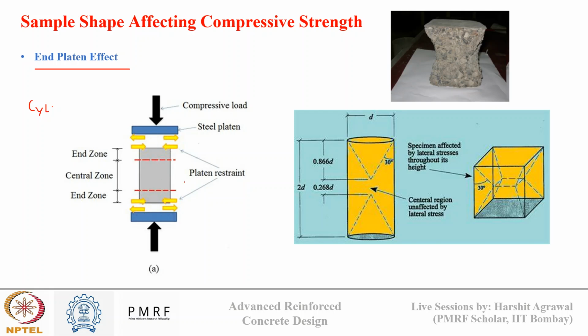So when we have a cube which is getting compressed between two plates for compressive load, you can see here these blue plates are steel plates and this is the cube in between. The surface of the cube which is in contact with the plates will try to be pushed outside. However, the friction between the plate and the cube will tend to resist this movement, so there will be opposite movement. The compression force will try to push the cube outside, however the frictional force between the plate and the cube will try to move the cube inside. This frictional effect is known as the end platen effect, and